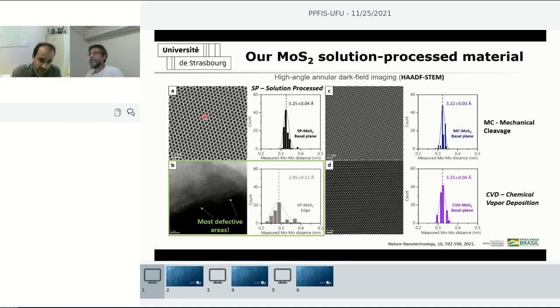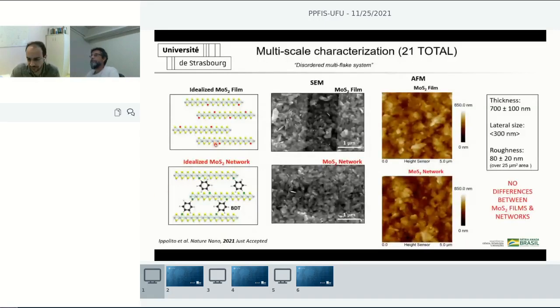And by comparing with the basal plane of the solution processed material, the basal plane of the molybdenum sulfide produced by mechanical exfoliation, and the basal plane of a material produced by CVD, you see that the molybdenum distance in the basal plane agrees for these three. So the values are pretty much similar, but our values are broader. This means that our material is very defective on the edges because it stresses the molybdenum bonds nearby the edges, and you can see clearly here the defects on the edge.